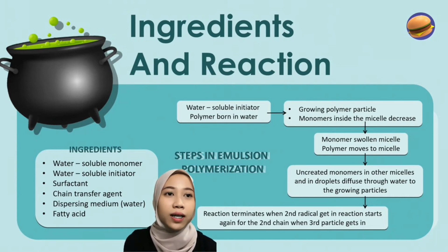Okay, next, surfactants or emulsifier. The surfactant must enable a fast rate of polymerization, and minimize coagulum or fouling in the reactor and other process equipment. Anionic, non-ionic and cationic surfactants have been used, although anionic surfactants are by far most prevalent. Surfactants with low critical micelle concentration are favored. The polymerization rate shows a dramatic increase when the surfactant level is above the CMC.